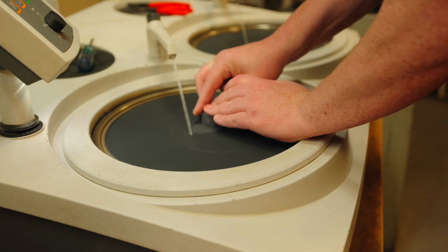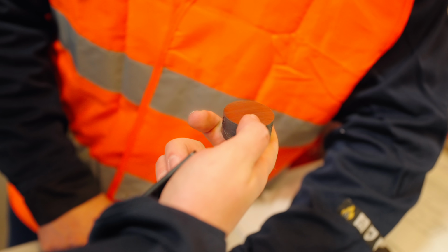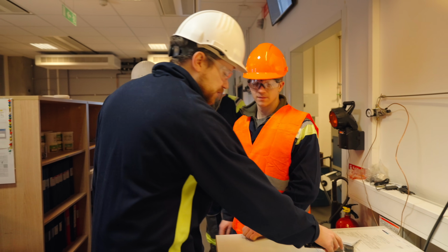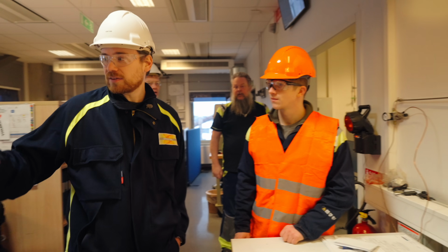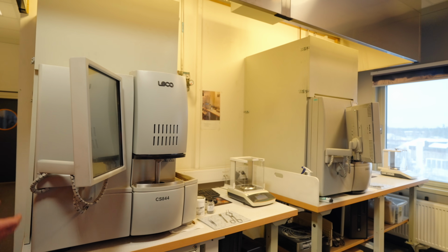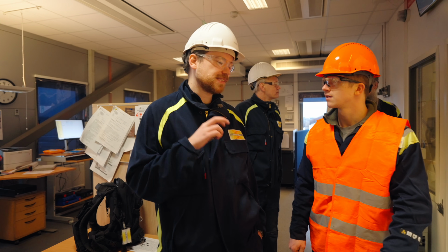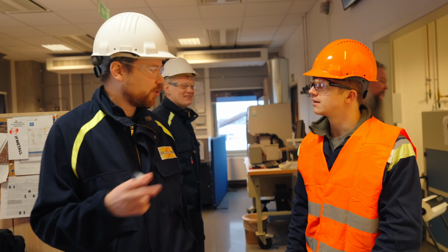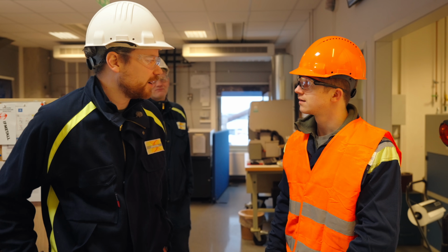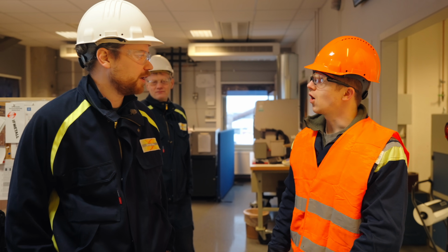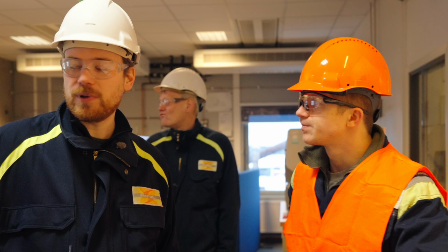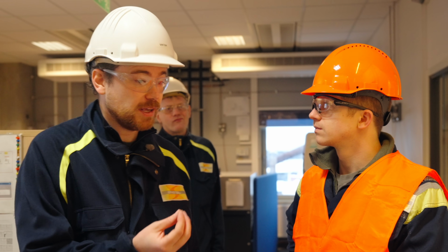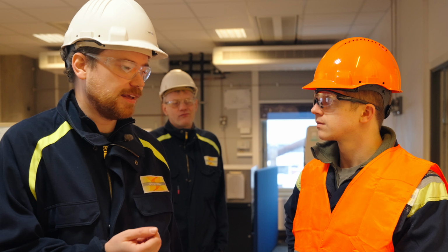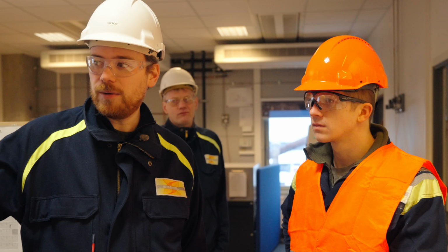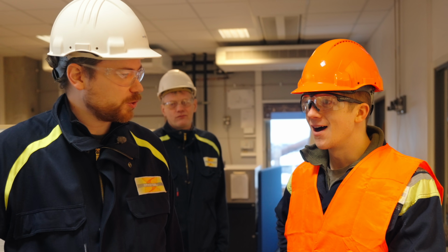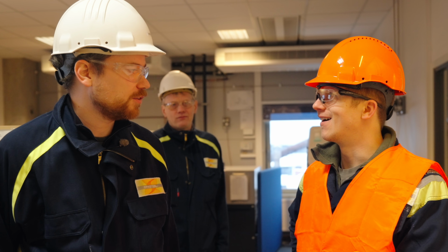And that has to happen right then? Yeah, so it's very time critical. In minutes? Yeah, it's very time critical. They check both on these type of samples, the XRF, we can go over and have a look at it. But what they also check is with this type of equipment, the LECO equipment, they check for elements that cannot be picked up with an X-ray. So carbon, sulfur, oxygen, nitrogen, very light elements you cannot analyze with an X-ray. So in this type of equipment, you heat up a small sample, either we can take powder or you can basically crush up a piece of steel. And it combusts it, and it uses IR spectroscopy to analyze the content of that steel.